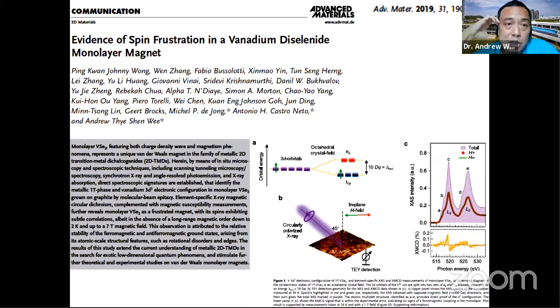The work was led by Johnny. So we used a whole range of techniques, including STM and so on. As you can see from this figure, that's the spin, vanadium 4+ as a single spin in a 3D orbital, and that's the crystal field splitting because of the octahedral crystal field. The important result is the XMCD of the vanadium peak you see on the right, C.